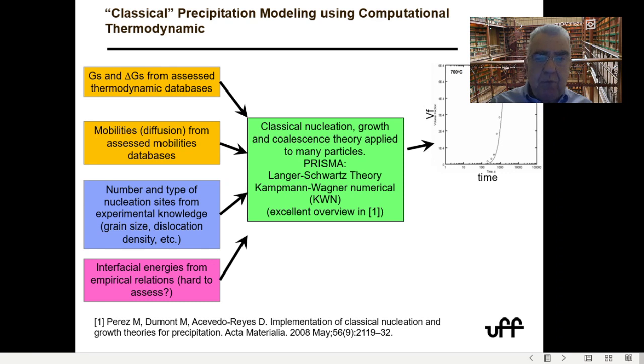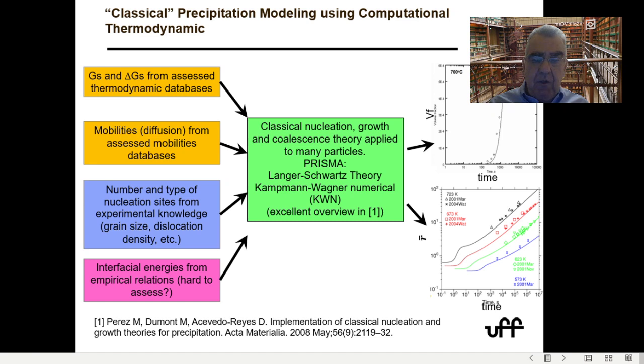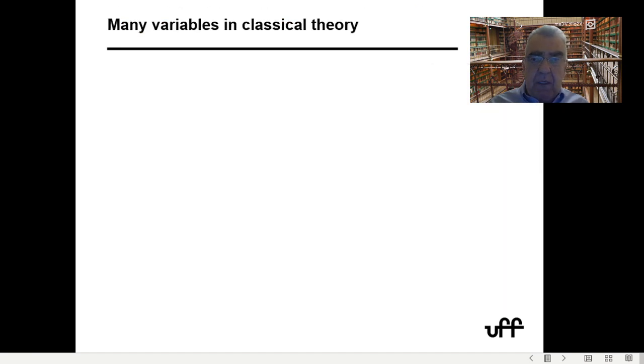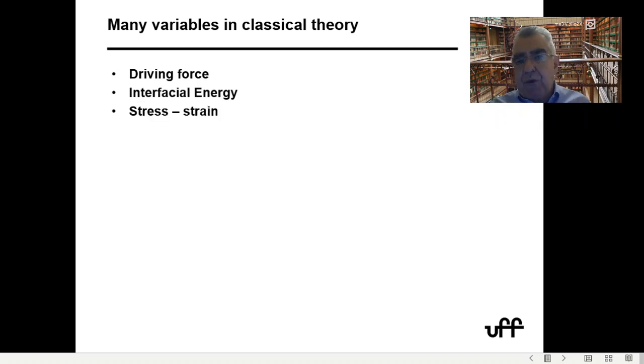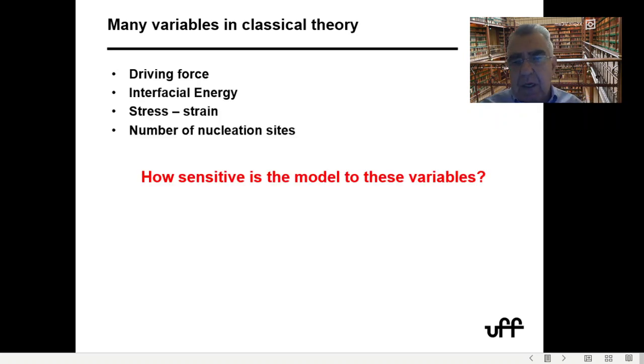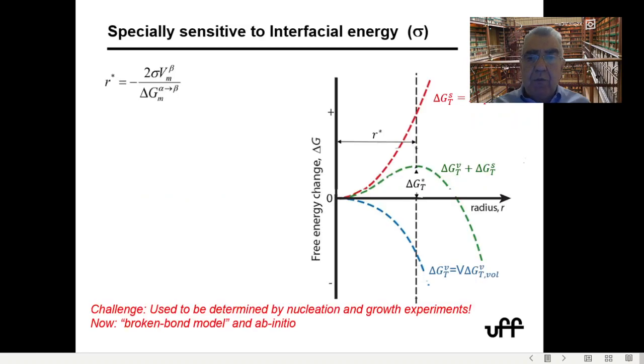And then you are able to make predictions using the classical theory, but not just by hand waving, but by using really correct free energies and correct mobilities. And this is very, very promising. Now, of course, the classical theory involves driving force, interfacial energy, stress and strain, number of nucleation sites. And so the question is how sensitive the model is to these variables. And the problem is it is very, very sensitive.